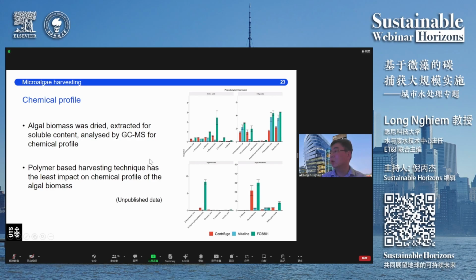And in fact, it is very well known, even with centrifugation, we will also have cell damage. So we use a technique called gas chromatography mass spectrometry to check for the individual chemicals inside the microalgae cell after harvesting. And the result is quite encouraging. Of the three different techniques that we use for harvesting, namely centrifugation and inorganic chemical and polymer flocculation, we see that polymer flocculation results in the microalgae biomass usually with the highest concentration of the organic content. Here we are looking at amino acid, fatty acid, organic acid, and sugar content.